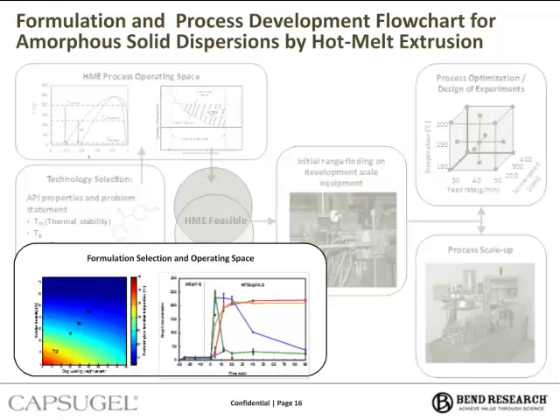So our approach to a formulation is to start with a binary system, meaning an API and a polymer, and add additional excipients as necessary to improve processing or in vivo performance. Now, formulation selection is based on matching that target PK profile and stabilizing the amorphous form of the drug to achieve an acceptable shelf life and to address any known chemical stability issues. And this is because the amorphous form of the drug, in many cases, degrades easier than the crystalline form.